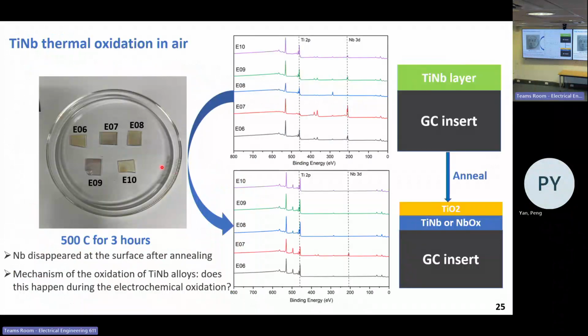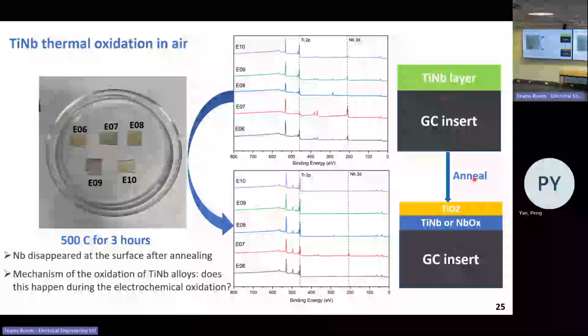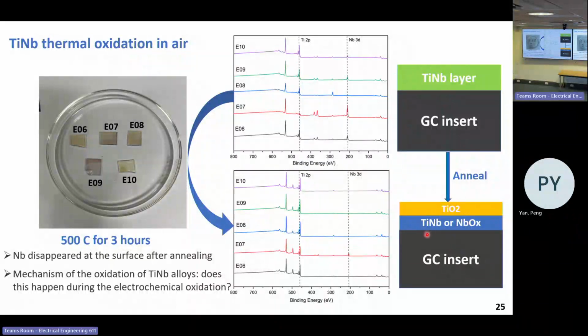In order to understand the oxidation mechanism of titanium niobium alloy, we first annealed the samples in air, and we could see the niobium 3D orbital disappeared from XPS, which indicates that after annealing, the phase titanium niobium has segregated, with titanium dioxide formed on top of the thin film.